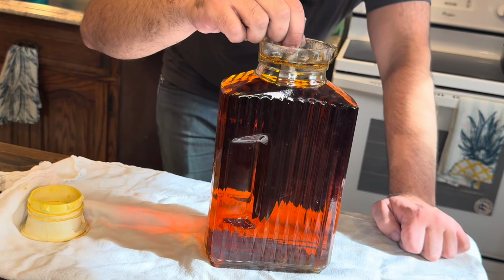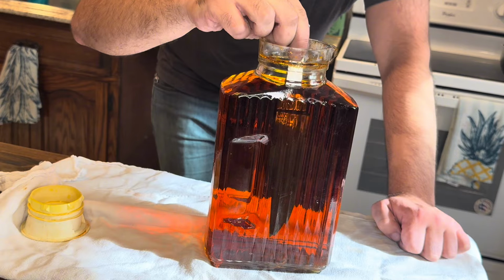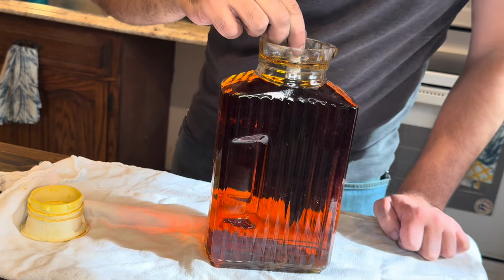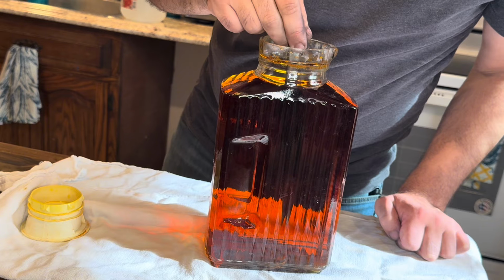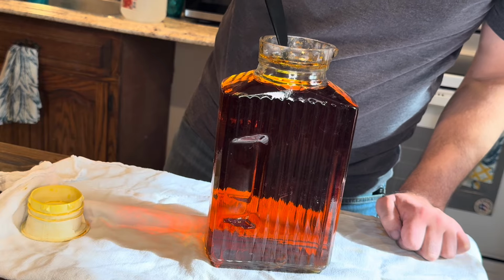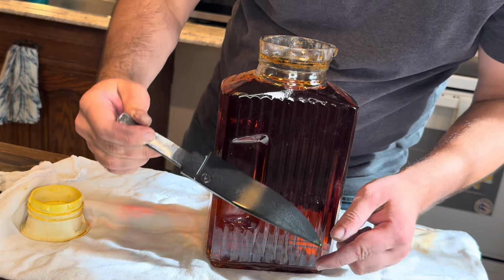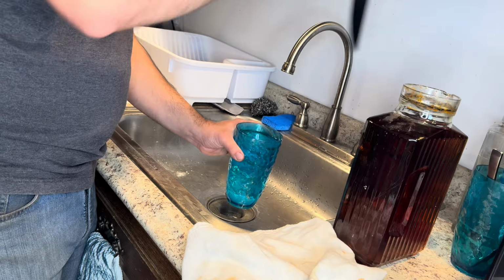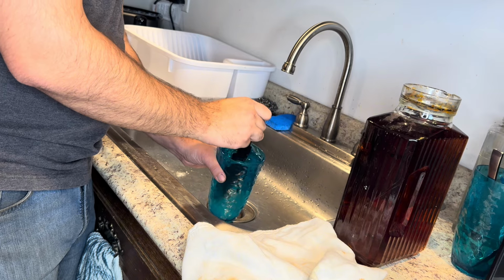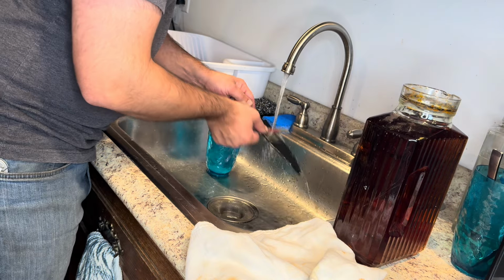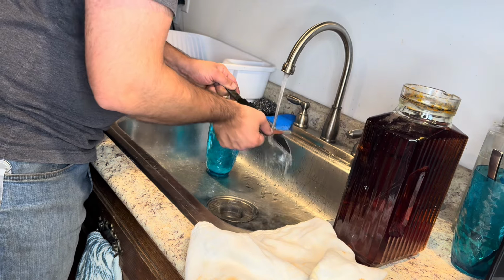You can see the pattern even after only a few seconds in the acid. This pattern is due to the different layers of steel we were forging out in the beginning of the video. The 1084 is just a normal high carbon steel, so the acid eats it away a little bit. The 15N20 has a little bit of nickel in it, so it resists the acid, and you can see it as a brighter steel in the pattern.